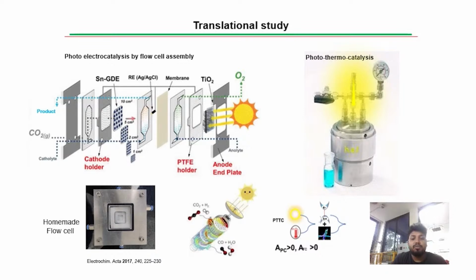Rather, what we can do is we can work in the interface of photo and electrocatalysis, which is called photoelectrocatalysis, and in the interface of photo and thermocatalysis, which is called photothermocatalysis. In the photoelectrocatalysis, if we use flow cell like electrochemical process, the activity and the current density can be improved, and there is a chance that at relatively lower potential, we may get the multi-carbon products up to C3 product also. For that, we have fabricated a photo flow cell like this, where we can directly use carbon dioxide. Therefore, there will not be a problem of CO2 solubility, and we can get much more product.